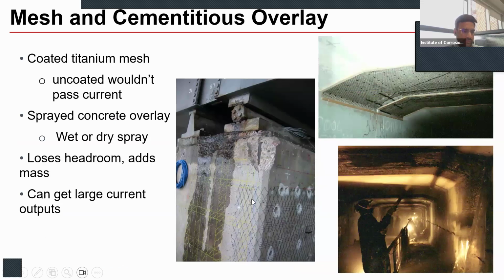Another system we have is mesh and cementitious overlay systems. Similar to ribbon systems, these are in the form of a whole mesh which covers your concrete sections. You can see this pier column where the whole MMO mesh is wrapped around the column, held in place using those plastic fixings. This system is generally sprayed concrete, an overlay system. Unlike the discrete anode system, the overlay here should generally be carbon-based grout or cementitious grout, which gets large current outputs from them.